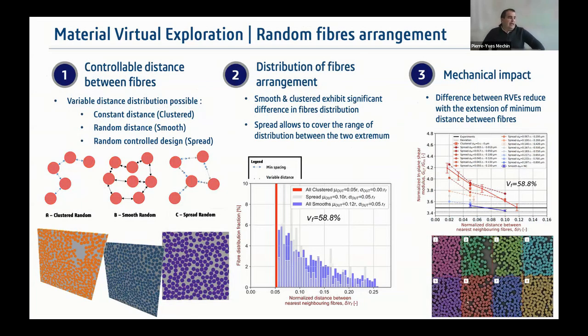Back to long fibers, we have been working extensively on random RVE models with different strategies to build them. Basically a smooth distribution, where we control the position of the fibers smoothly distributed on the microstructure. We have some cluster models where we exhibit some resin-rich areas. It has been extensively published with different strategies to create resin-rich areas, not necessarily an easy methodology. I think this one is really useful because at the end we have a unique spread random RVE, which is able to create all the combinations of fiber arrangement that we can have in real life.